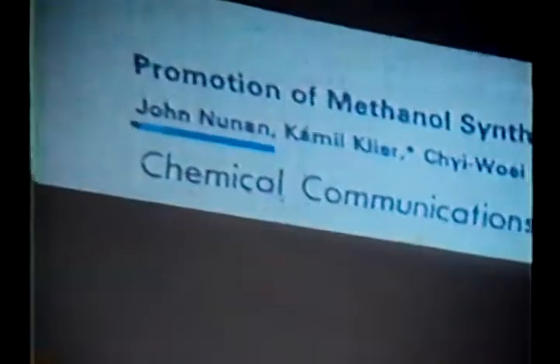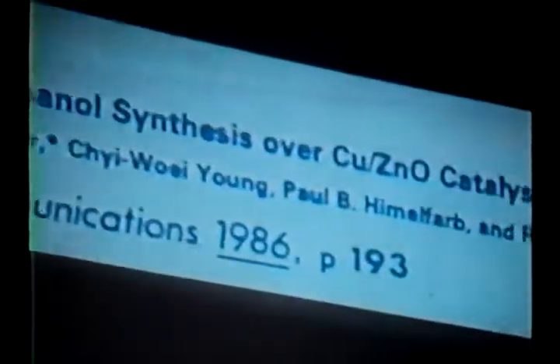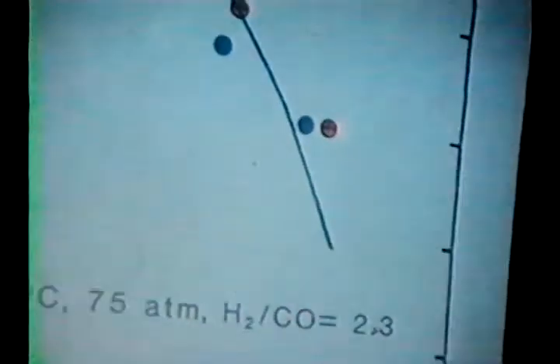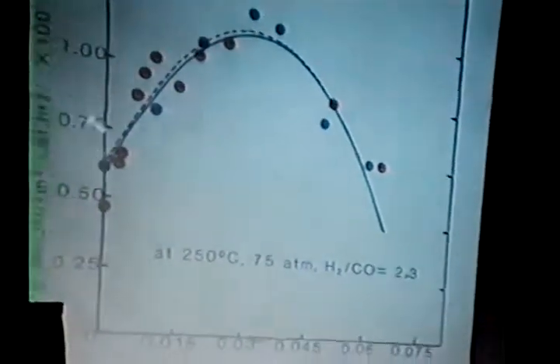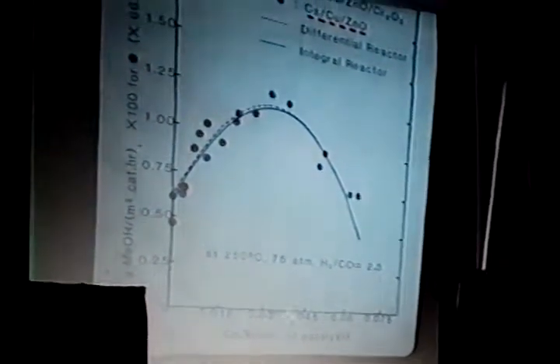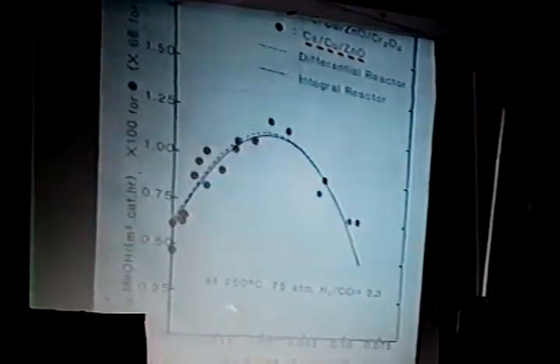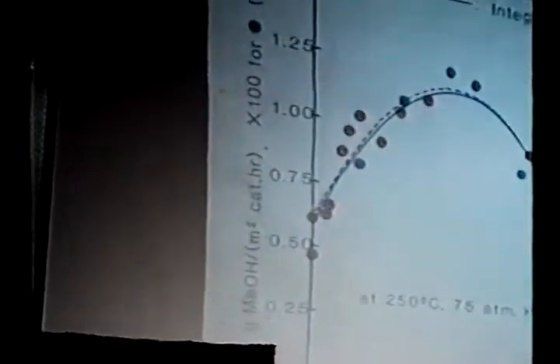In the copper-zinc system that we studied earlier, we actually observed a similar maximum as I reported to you on moly disulfide with cesium, but in this system, a minuscule amount of cesium is necessary for producing such a maximum. And that maximum is shown here on two catalysts. It is the maximum in which this system promotes methanol synthesis by cesium doping. If you compare these levels, they are orders of magnitude lower than the levels of cesium in the moly disulfide system. And the reason for this is that the cesium disperses.